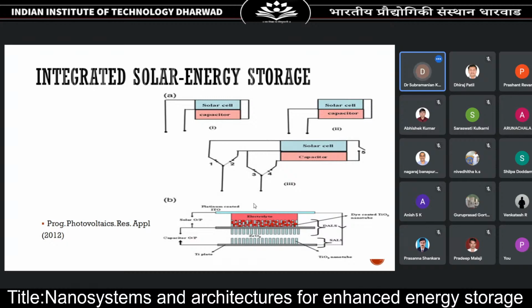where you have an anodized titanium plate. You can see the nanotubes on either side of the plate. On one half of the plate, the solar structure is built up. What is built up is a dye-sensitized solar cell, where the dye is coated on the TiO2 nanotubes, and then you have the redox electrolyte, and then the counter electrode, which is platinum-coated ITO. So the solar cell functions on the DSSC mechanism.